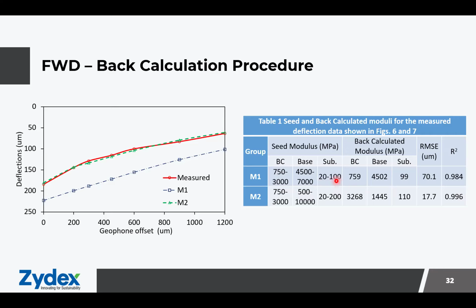Now, if we consider this input into KGP back, it will give us the results, but it will not indicate whether the bowl has converged or not. The back calculated modulus that it will give will look like this: it will give 759 for the BC layer, for the base it will give 4502, and for the subgrade it will give 99. But if we now put this modulus value into IIT PAVE and calculate the surface deflection corresponding to these offsets, we can measure the deflection bowl.